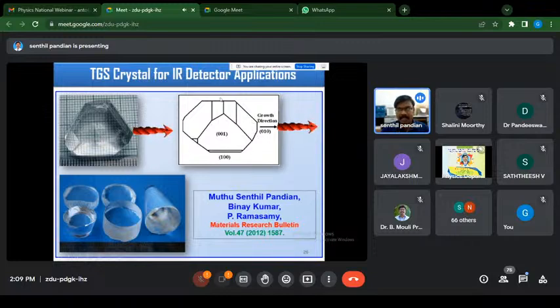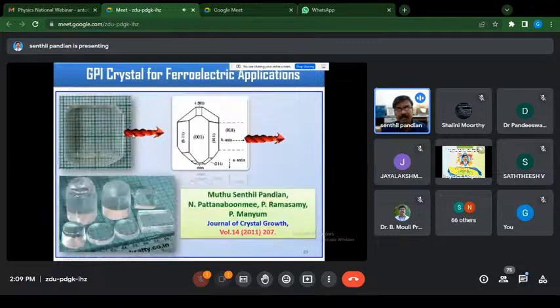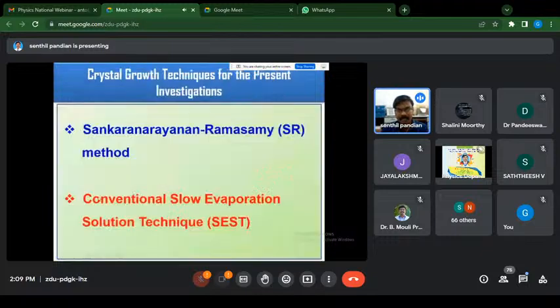So the other portion will be cut away after cutting this polar B direction. We cannot use it. So again, we have to grow the crystal by this conventional method, and we have mounted the seed crystal in the SR method, and we have to grow the crystal along its polar B direction, and we have reported it in a journal. This is the glycine phosphate. We have grown the crystal along its polar B direction, and we have successfully grown the crystal by this SR method. So the crystal growth techniques for the present investigation, I mainly focus on this SR method and then this SEST method.